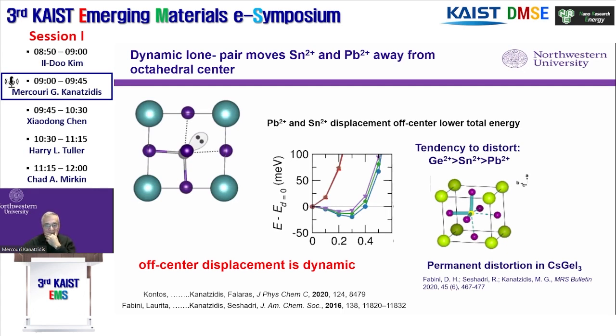So why are these things happening? First of all, there's a clue in the fact that only lead and tin are the high-performing materials. If you replace them with other things like cadmium or strontium or other systems, they don't perform at all. What lead and tin have in common, being 2+, is the lone pair of electrons. These are group 14 elements, so in principle they can oxidize all the way to 4+, but here they stop at 2+, and so they have a lone pair of electrons. We know from the chemistry of water and ammonia, which are bent molecules, that the lone pairs of electrons in oxygen, two of them, want their own space, and they make the water molecule become bent. The nitrogen lone pair wants its own space, so it makes the ammonia molecule pyramidal.